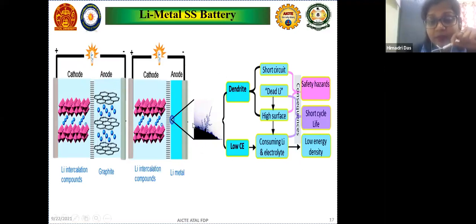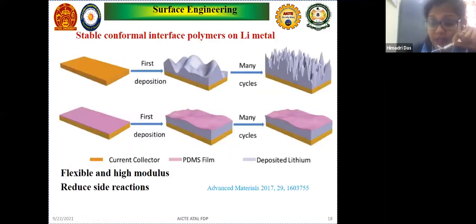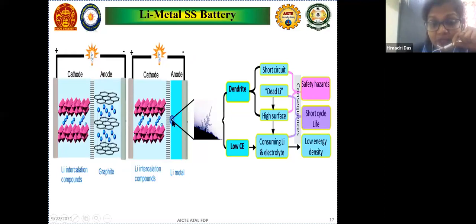Now what exactly will happen when this dendrite grows on the lithium metal surface? It will lead to short circuit of the battery, and dead lithium will be created, as well as it will take a high surface area. So coulombic efficiency will reduce because there will be a huge consumption of the lithium as well as electrolyte. It will just result in safety issues and short circuit. So lithium metal batteries in solid state form are also not giving the proper output we are looking for. But this dendrite formation can be reduced by different technologies, by different approaches.